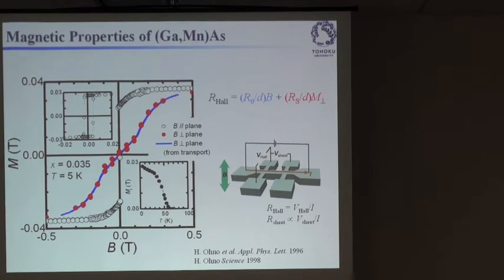This is because the Hall voltage, the blue curve here, is a voltage divided by the current we flow, so we call this Hall resistance. So Hall resistance or Hall voltage developed across this Hall probes closely follow these red dots, which is the result of measurement of magnetization.